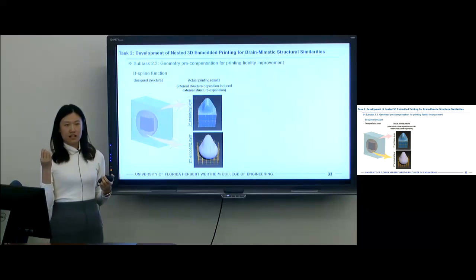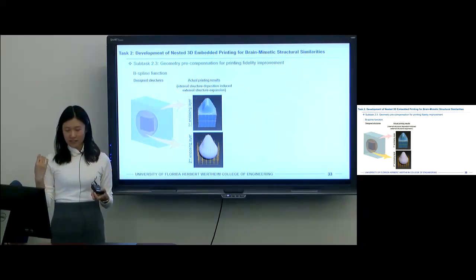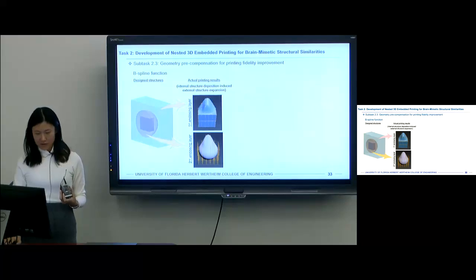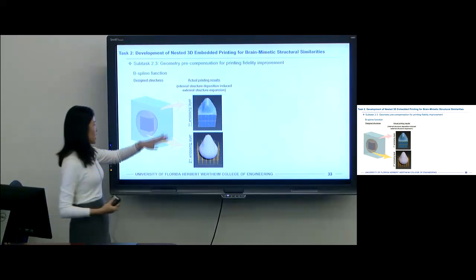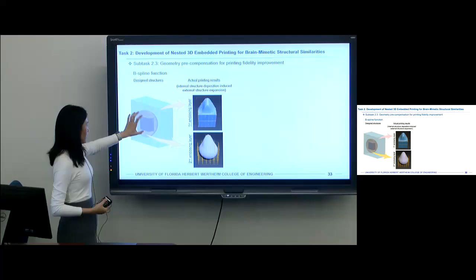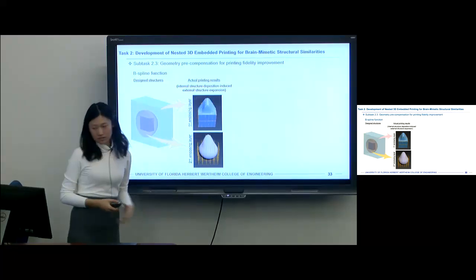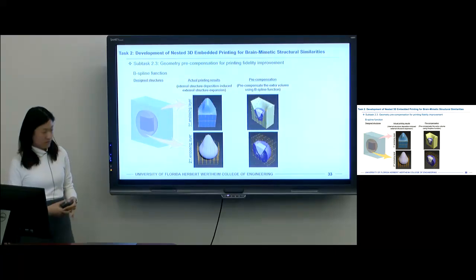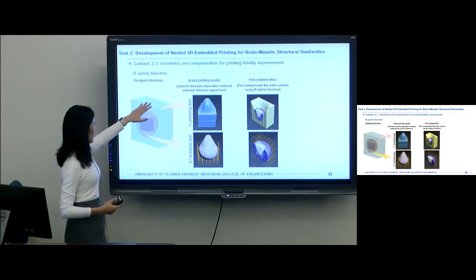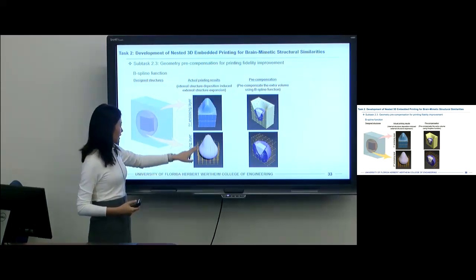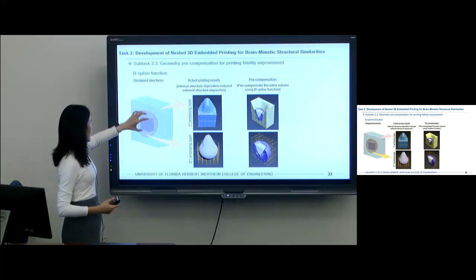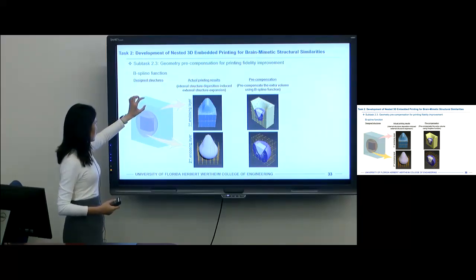Other than the defects or printing fidelity loss during the depositing process, there are other factors that could affect the final printing fidelity. We call it the volume deposition induced printing fidelity loss. That means when we try to deposit a multi-layer structure, the outer layer of the structure will be distorted. Here is the 3D reconstruction of the printed structure. This is the first enclosing layer, like the outer cube shown here, and this is the secondary enclosing layer, which is spherical. That means when we deposit the second layer, the first layer will be distorted. And when we try to deposit the third layer, both the second layer and the first layer will be distorted.